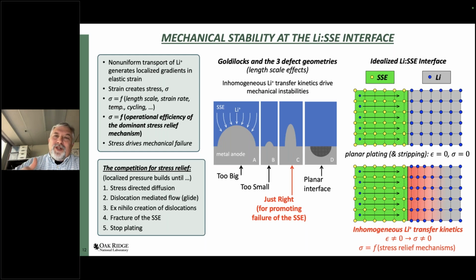We've got stress-directed diffusion, dislocation-mediated glide, and then the one we're desperately trying to avoid is fracture. That competition creates something of a Goldilocks problem for us. The idea here is that lithium ions are preferentially plating into any non-planar regions of the interface, and the pressure builds inside that defect until one of those stress relief mechanisms is activated: diffusional flow, glide, or fracture.